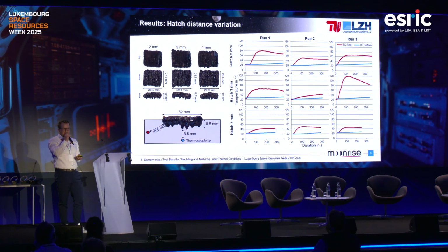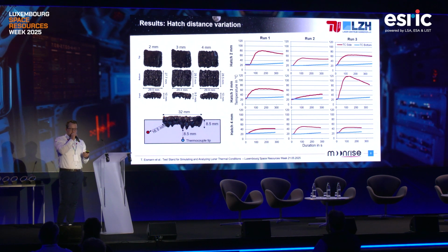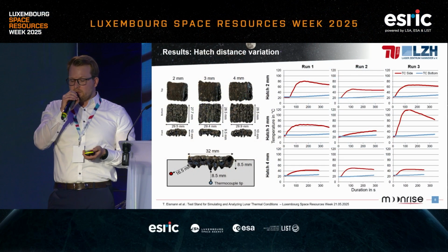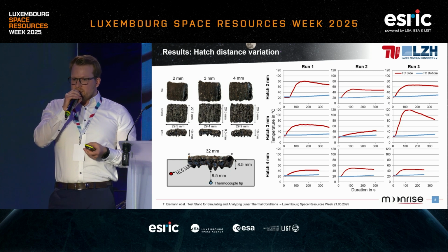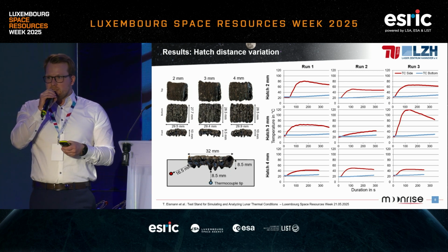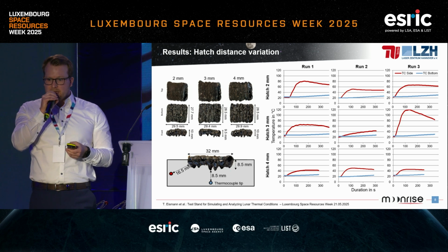That was expected, but what wasn't expected is what the thermocouples have been measuring, because the red thermocouple on the left, on the outside, is actually further away from the heat source, from the sample in that case, than the blue one on the bottom. So you would expect that the blue one heats up more than the red one, but it's the other way around, indicating that there is some additional heat source from the outside heating up the powder bed, like radiation that gets reflected, for example. And for us, it's important that we know that and that we can measure that, because otherwise we would have some influence that we couldn't take into account.